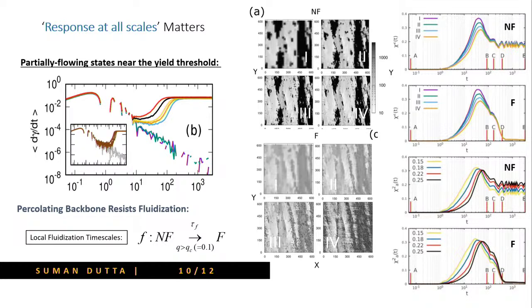If we try to compute this susceptibility out of all this spatiotemporal heterogeneity, for the non-flowing case we see that this backbone and the associated fluctuation remains for a very long time, while for the fluidization, all the region and the response becomes 0 at long time. That ensures that the system has fluidized at all scales.